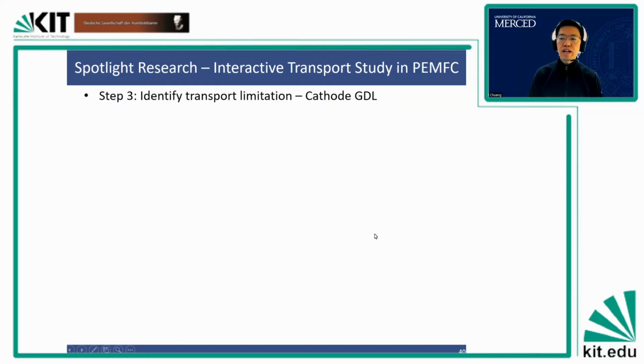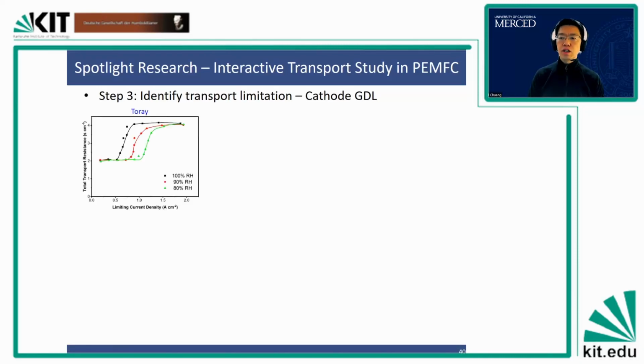Step 3, we identify the transport limitation. We apply the tools on this material, the Toray material. On the y-axis is the transport resistance, this is the oxygen transport resistance. As you can see, this resistance is actually not a constant. When the current density increases, the transport resistance also increases. This is a sign of liquid water condensation.